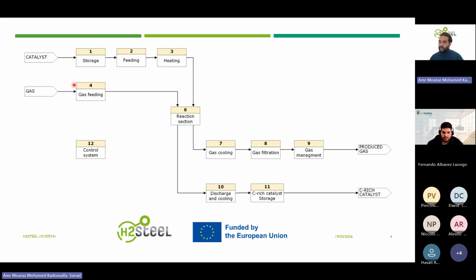The catalyst is then moved into the reactor where the interesting stuff happens. And here the gas is also fed into the reactor from the gas feeding line, allowing for the reactions to happen, the necessary reactions for the production of hydrogen and the deposition of carbon. After which the carbon is moved into the cooling and discharging screw. It's a screw that also controls the cooling of the system, and the gas goes through the gas cooling filtration and then the gas management system, and then later on it goes into the micro GC for gas analysis and further reductions.